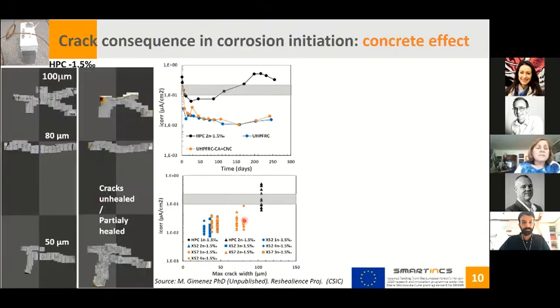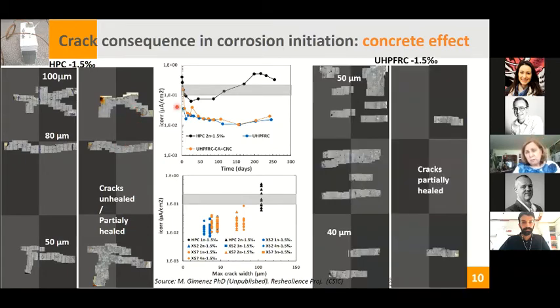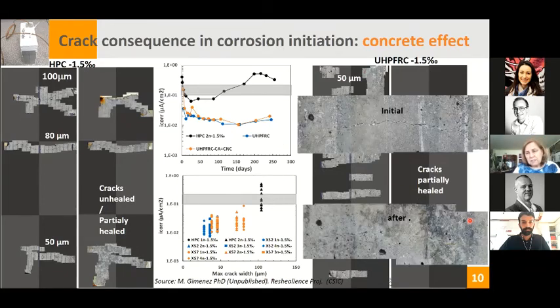What we observe in this case with the HPC with 1.5 per mille, this is the initial, but after a period exposed to the environment, there are some cracks that are healed, but some others are not healed, so the corrosion was initiated. In the ultra high performance concrete, we have a different pattern of cracks, different size, and some of them are healed, and even having some unhealed cracks, corrosion has not been initiated yet. Different reasons can be contributing to this performance. This is the initial, and this is after the healing.